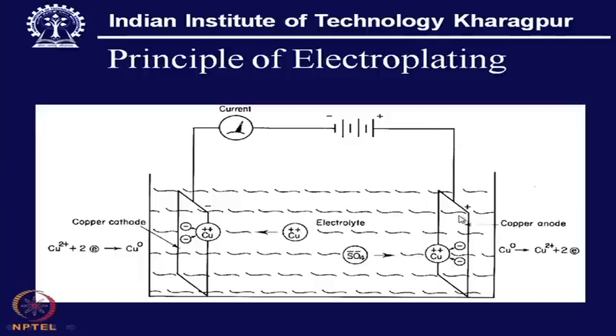Now, what is going to happen in this case? Because of this negative polarization, copper ions will collect on this surface, and the electrons from this path will move on this side, because it is this copper ion that is going to be neutralized by this electron, and it becomes neutral copper that is collected on this surface. However, this electron will flow on this surface, and at the same time as the electron moves, we have release of copper ion, and that copper ion goes into the solution to combine with the sulphate radical. And in this case, what we see is that with migration of copper ions towards the cathode surface, there will be a deficiency of copper in the solution, and that will be continuously replenished.